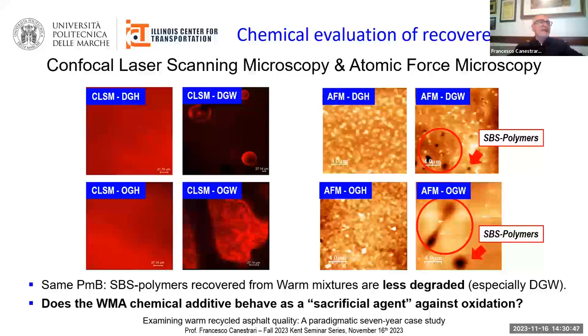The confocal laser scanning microscopy and atomic force microscopy allow us to investigate the bitumen microstructure and SBS polymers dispersion. The results shown in the pictures clearly indicate that the SBS polymers are less degraded for recovered binders from warm mixtures, especially in the case of dense-graded mixtures. This result could be due to the chemical additive used for the warm mix asphalt technology, which could behave as a sacrificial agent against oxidation. Thus, the lower production and mixing temperature of warm mixtures preserved not only the bitumen from aging, but also the degradation of polymers.